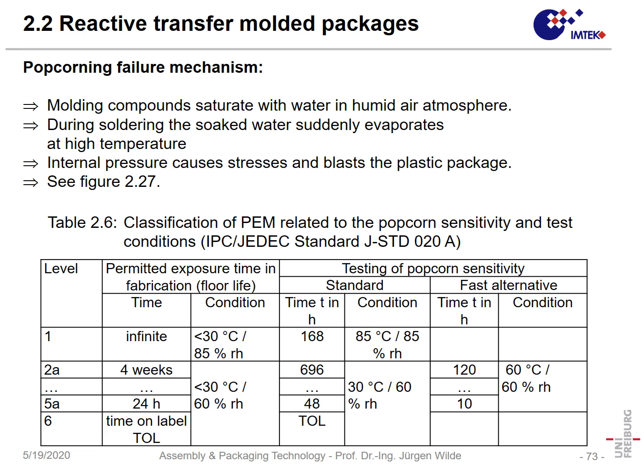The molding compound saturates with water. Water is mainly at the interfaces. During the soldering of the device on the board, the water suddenly evaporates. Internal pressure will be high, and it causes stresses, and it blasts the plastic package. So that means we have some damage here. And so popcorning has to be tested.